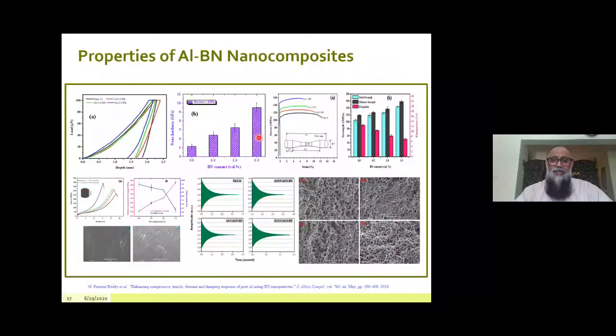And these are some mechanical properties as I have discussed earlier. With the increasing amount of boron nitride in the aluminum matrix, we have seen improvement in the tensile strength and compressive strength, and we have observed a reduction in the elongation. So these are similar results to what I have explained earlier.